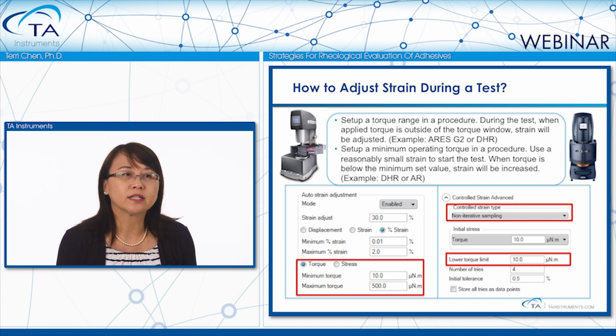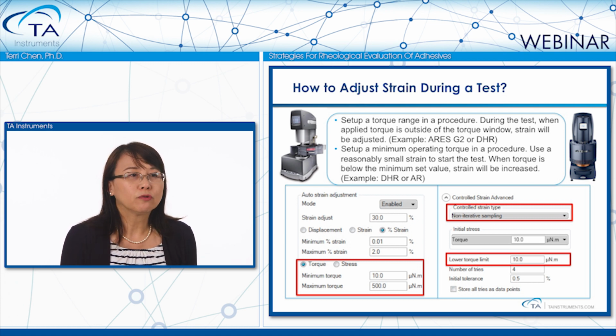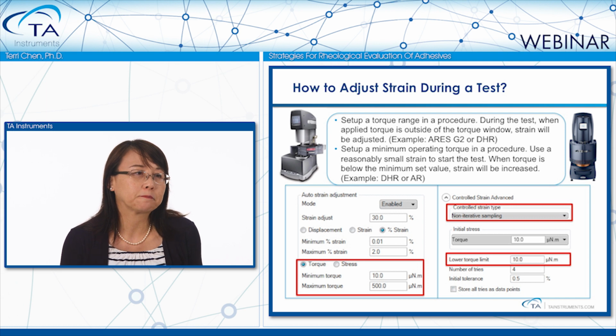This torque window is not the instrument spec. It is particularly selected based on the fact that the measurement is within the linear viscoelastic region of the sample and also ensures a good signal-to-noise ratio. When the test strain requires a torque that is outside of this window, the strain will be adjusted.